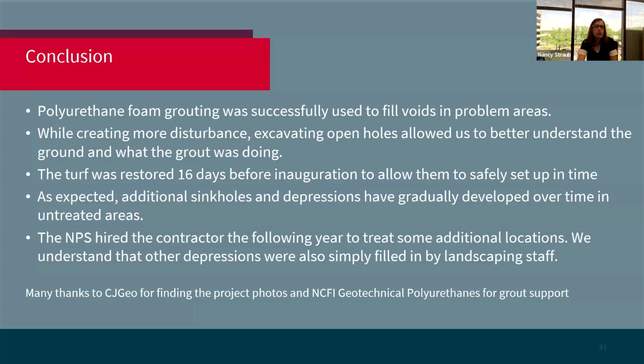In conclusion, for this grouting project, we found that the polyurethane foam grouting was very successful in really sealing up and filling a lot of the voids. The vacuum excavation, while it definitely created more disturbance, was very helpful for, first of all, getting past a lot of those cobbles, but it also revealed to us the extent to which the voids below ground were cross-communicating. We were able to get it all done and cleaned up with 16 days to spare before inauguration, which gave the National Park Service time to get everything set up.